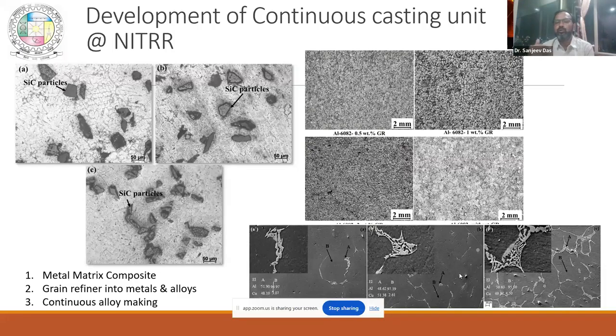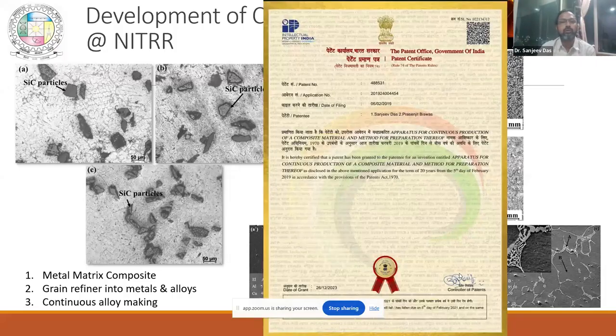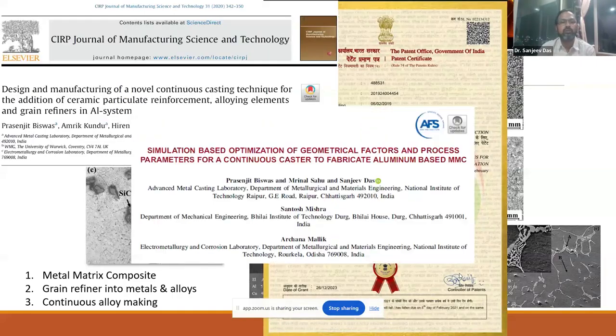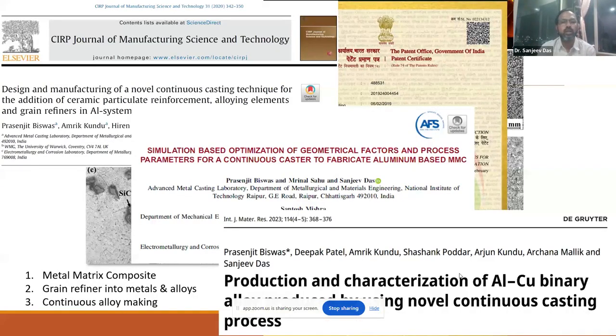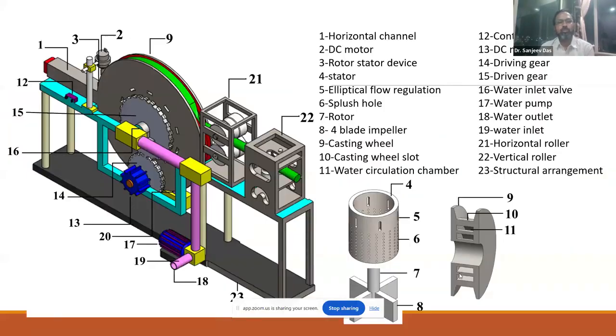And the beauty is you don't need to stop. You can continuously do this by this continuous process. You can change the alloy, you can change the percentage of grain refiner, you can change the amount of particle addition in it. We have the patent for this process also, and a lot of publications are also there which you can follow. Now let us come to the nanoparticles.